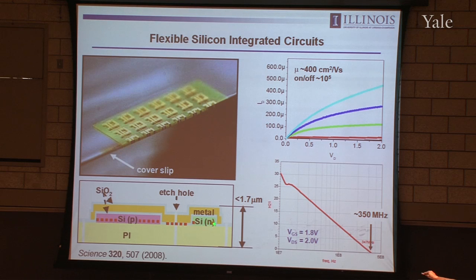You overlap that neutral plane with the brittle silicon layer by choosing the underlying plastic substrate with an appropriate thickness to do that. So in this case, the entire circuit is just a little over 1.5 microns in thickness, able to bend to a very sharp radius of curvature, about 25 microns in that case. At the same time, you retain wafer scale characteristics in the individual switching devices and the integrated circuits you build with them.